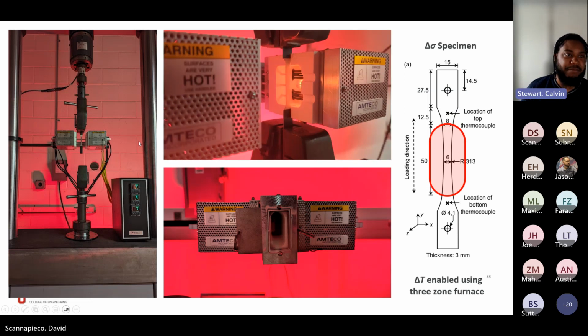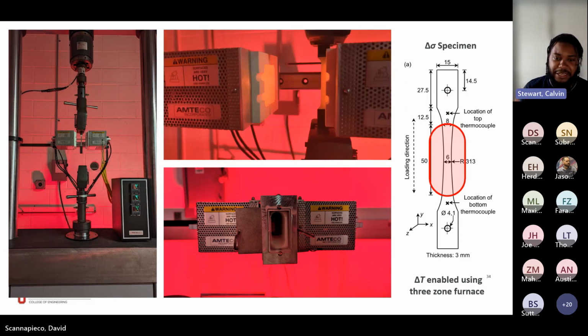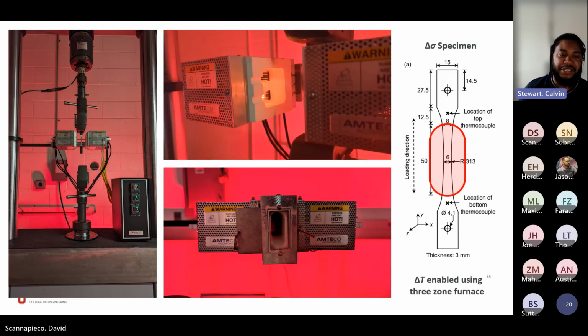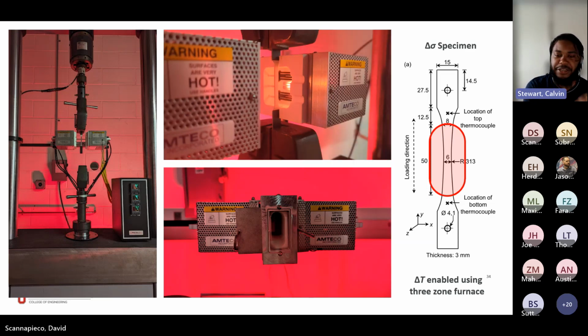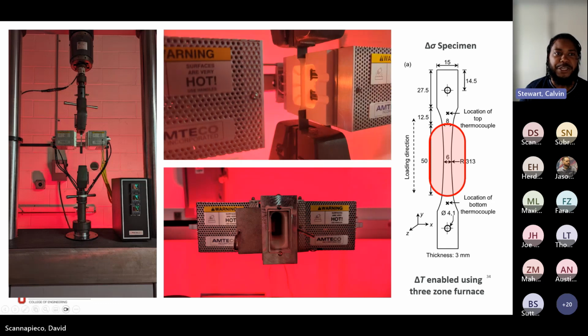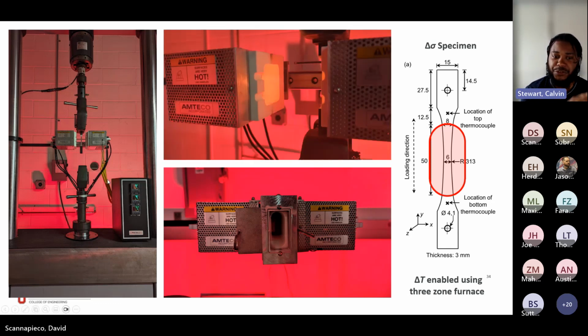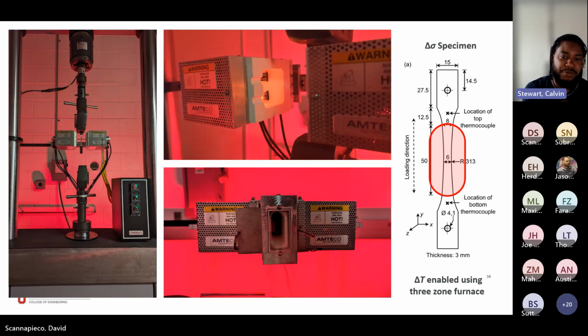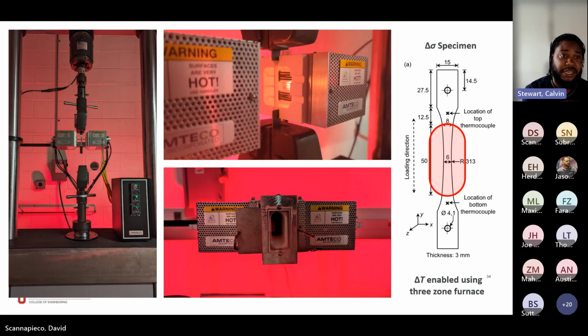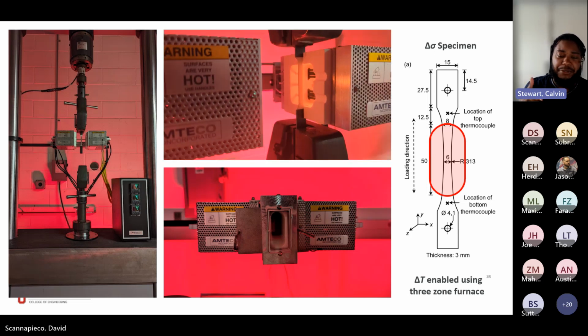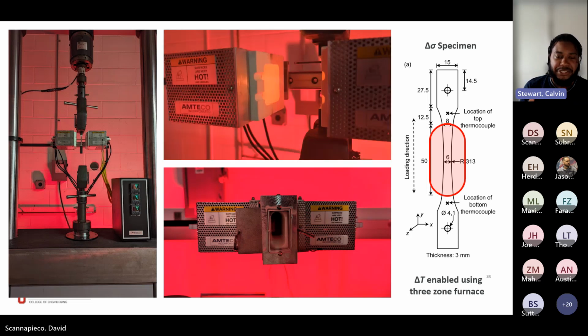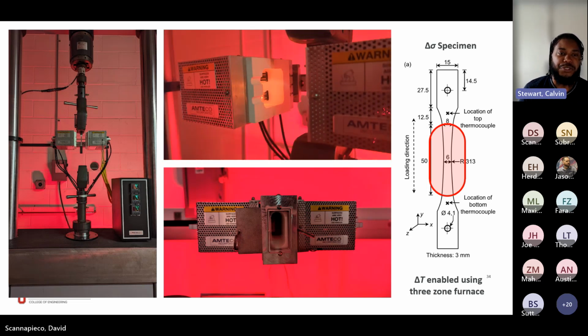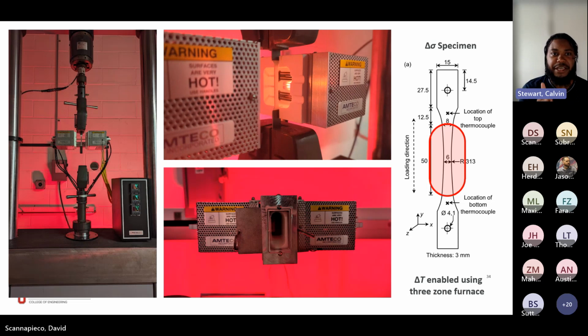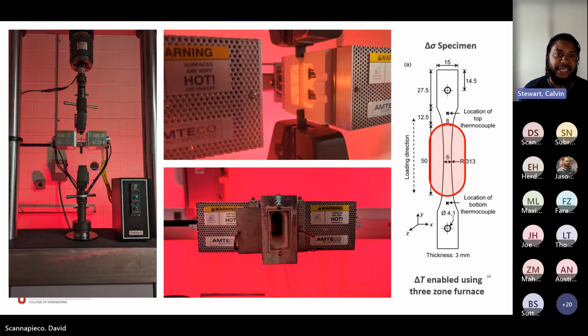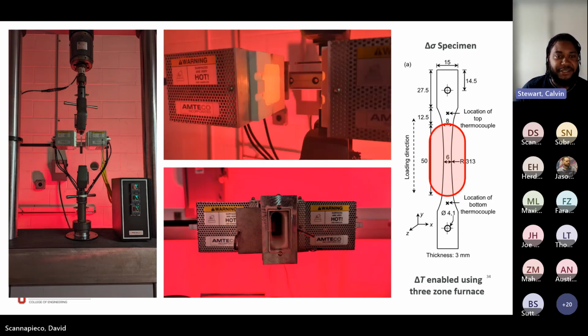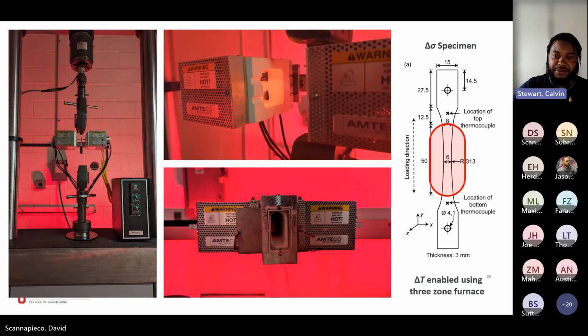So in this new lab that I'm building, we've been developing a test setup to do exactly these experiments. We've got an MTS machine set up with a 3-zone resistance furnace that goes up to 1400 degrees Celsius. And we also have an optical viewport that allows us to actually see the sample when we're testing. So we have a delta sigma specimen design that has a very slight radius, right?